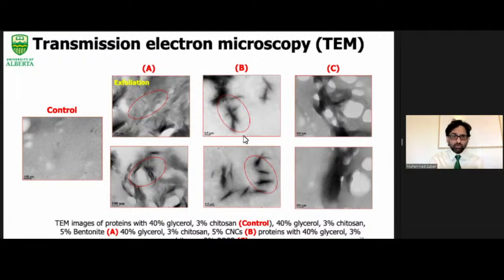So among all, from this, we can conclude that the transmission electron microscopy shows that in case of bentonite-containing films, the distribution of the nanoparticles is better as compared to the other nanoparticles. That might be the reason of the maximum mechanical strength of the protein films by the addition of the bentonite as compared to the other two nanoparticles.